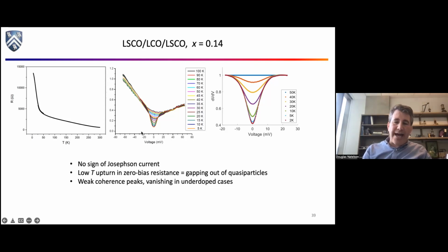And then I can also look at what's called the differential conductance. I can look at basically the slope of the IV curve. And what you find is that it's always got some curvature to it. At low temperatures, this real dip starts forming at low voltages. So this is really a sign that superconductivity is kicking in. And this is that dip I was telling you about, where you're kind of eating up all the ordinary electronic states that are available. You can kind of replot this data in a normalized way, and you can see, yeah, at 50K, when the thing's not superconducting, this is pretty flat. But as you cool down, it starts really getting cuspy.